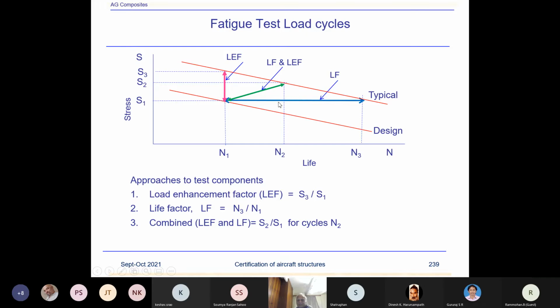Another option is, instead of applying life factor, you can apply a load enhancement factor totally. So that means this is my design stress. I must test a structure at the level of S3. Okay, so this is my load enhancement factor, meaning S3 divided by S1. And this may come out to be 20% higher or 25% higher. That means you are applying a much higher stress level. And due to the much higher stress level being applied for the test, you might start failing the component somewhere, like metal fittings. They might fail. Some joints might fail. So there's always a risk, either in using this one or in using probably this one.